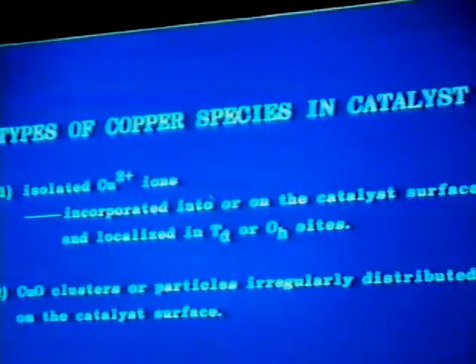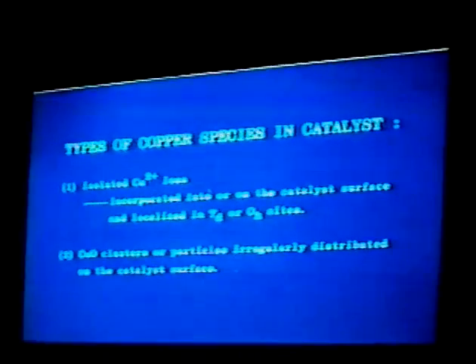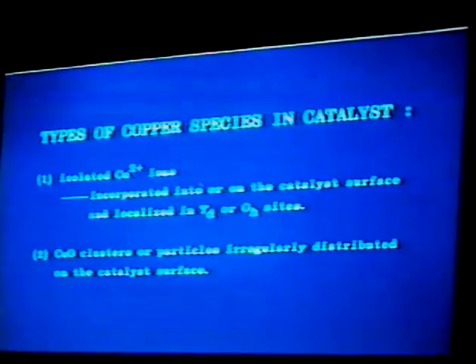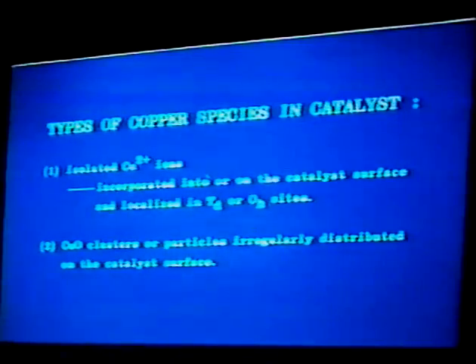If we think we probably have some different types of copper species in this catalyst, the first one is probably isolated copper 2 ions, probably incorporated into or on the catalyst surface. However, we might omit this one, probably located in a tetrahedral or octahedral site. The second one is the copper oxide clusters or particles, which are irregularly distributed on the catalyst surface.